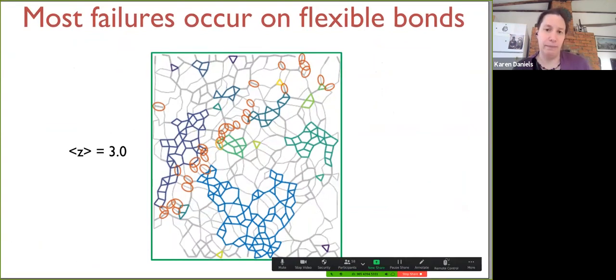And lo and behold, this is one example, but it's very intriguing. Every place that's an orange circle is a spot where a failure occurred. And it sure looks like those failures are clustered along the floppy regions between the rigid regions. This pebble game analysis, which describes where the rigid regions are, at the same time also tells you the not rigid regions, by elimination. And those seem to be the bonds that are more flexible, more able to bend. If you're more able to bend, you can more easily be pushed past the point of failure for the plastic material, and therefore you're the one who breaks. Being in a rigid cluster actually protects the bond from having too much torsion, too much stretching, too much compression, and therefore they don't break. So this is illustrative of something that may be a broader effect, but for which we do not have good statistics.